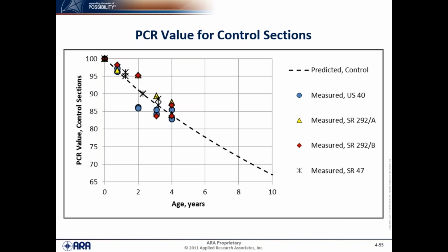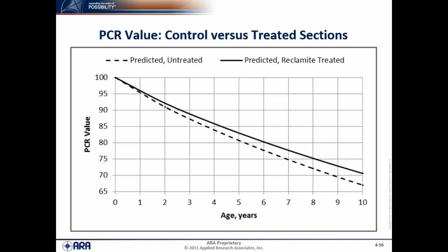So what we did was we took all the PCR values for the control sections as well as the treated sections, and we used a standard equation or standard relationship that's in the report to determine how PCR is going to change over time using actual test data, at least at the beginning. So basically this just shows a regression of PCR values of the control section along the y-axis versus time. And this just shows the variability in the data. And then we took that one step and did the same thing with the treated sections on the average.